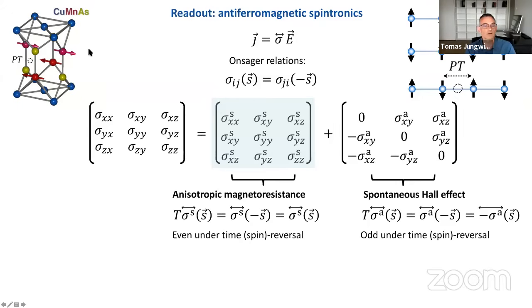Now, when I look at our workhorse collinear antiferromagnet copper manganese arsenide, it has exactly this symmetry property. It has the combined PT symmetry, so the anomalous Hall effect is not present in the system. So we can only work with the symmetric